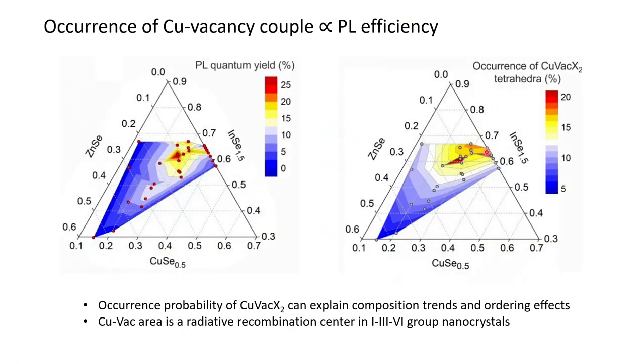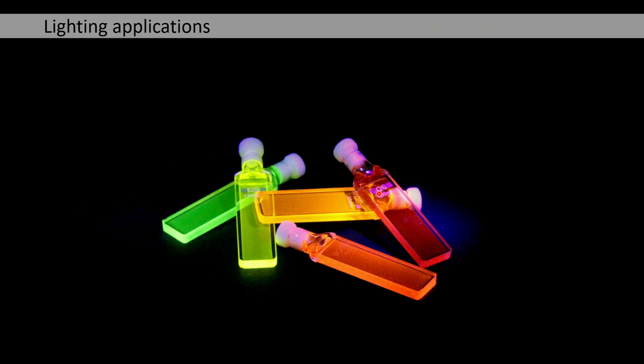And you can check it yourself here. On the left side of the slide, you see the experimentally measured luminescence efficiency, and on the right side is the occurrence probability for the copper vacancy containing units. So they pretty much match each other. Why is it relevant? It's relevant for lighting applications. These are the colloidal vials of materials which we have. When we shine high energy light at them, they shine back a very uniform, very clean light. And of course, the most efficient light is coming from the ordered compounds.